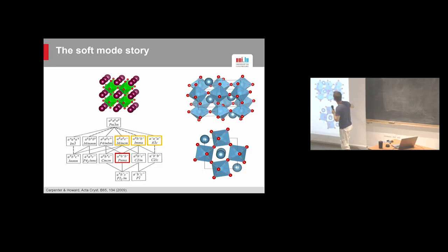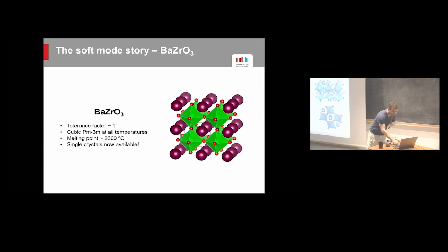So this here would be the Pnma perovskite, not the best picture, and this here would be an image with just tilt in phase in that direction. This is the general context, and this is now how barium zirconate was of interest for us. Here is a bit more context. It's cubic at all temperatures. The melting point is really high, so that's why it was difficult to get good quality single crystals, which has hampered the research for a while.